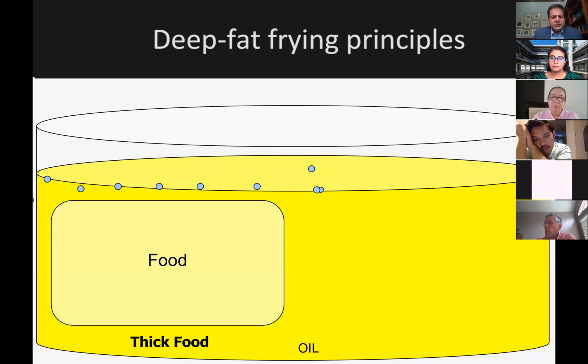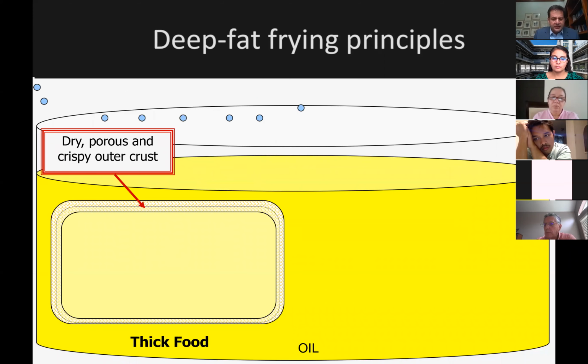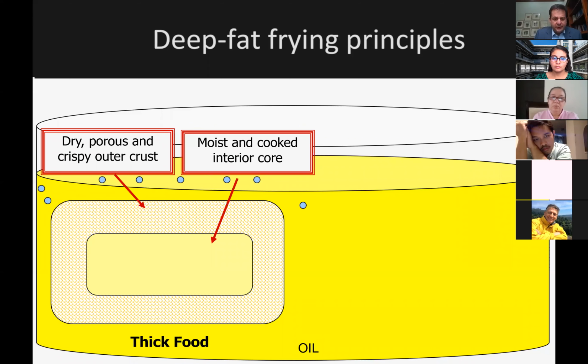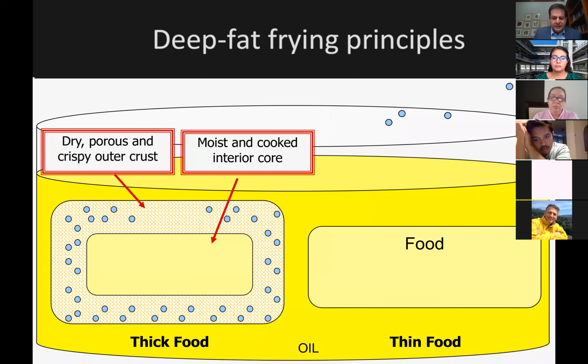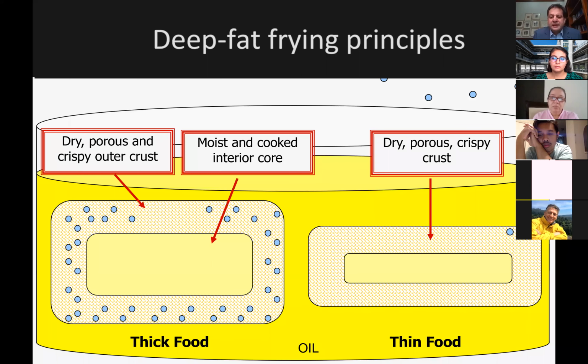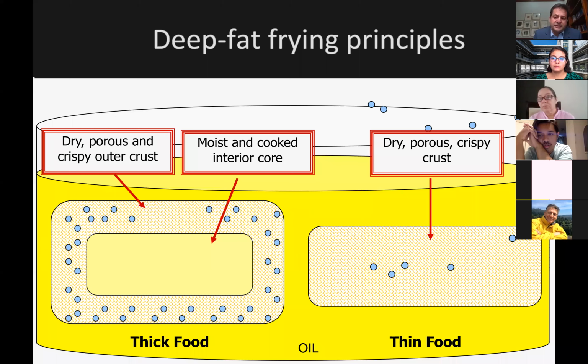You can see that once the food gets into the oil bath, it will heat up on the surface, and then water will begin to evaporate. And as this process continues, the evaporation front will move towards the interior. And this will lead to a composite structure composed of a dry, porous, and crispy outer layer, denominated crust, and the moist and cooked interior, denominated core. This is what happens in a thick product. A thin product is very similar. The only difference, as you might guess, is that finally, after the evaporation is maintained, the product becomes just a single crust. That means a dry, porous, and crisp structure, similar to the crust.